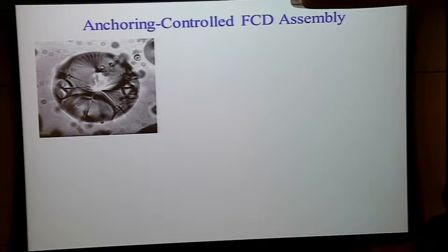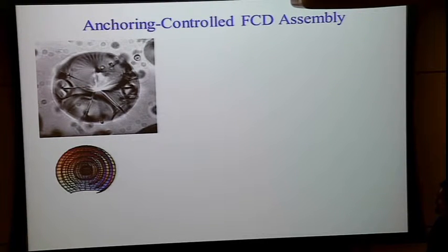So with this now you can explain analytically things like filling of the droplet. So here what you're dealing with, you start with the concentric system of spheres, and then you kind of facet it with the focal conic domain. That operation saves you the surface anchoring energy because you replace the homeotropic orientation of molecules at the surface with tangential. That saves you the surface energy.